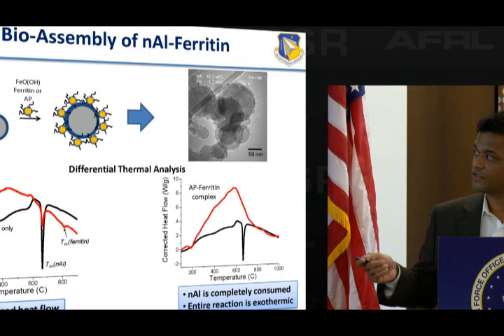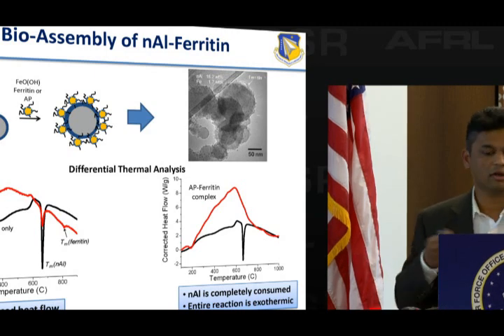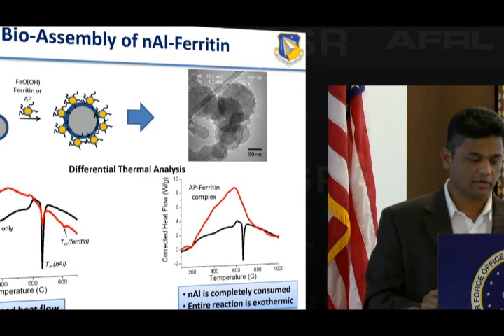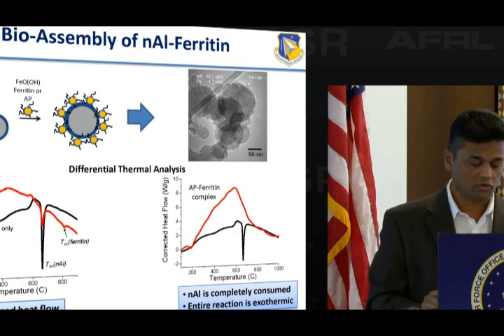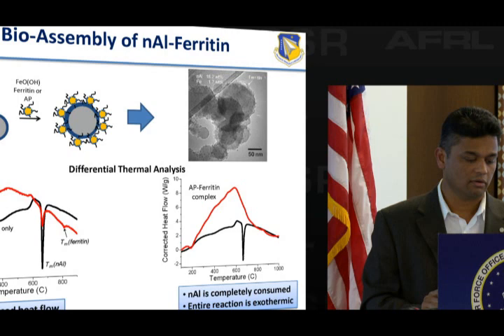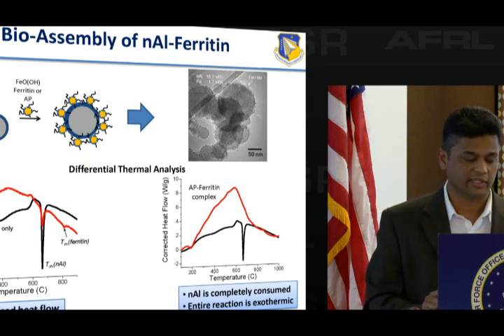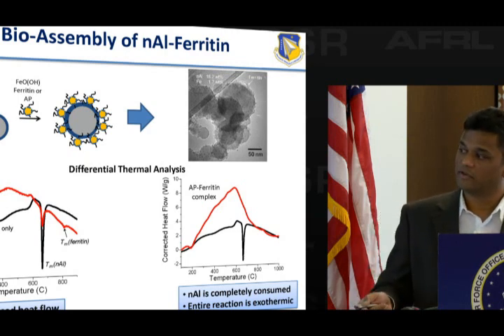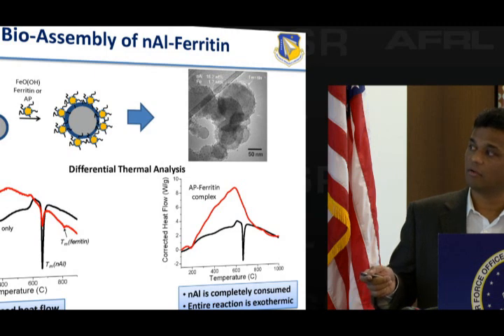So there's already iron oxide in there. Or you can bring ammonium perchlorate and load it in or put it on the outside. We tried all different kinds of tricks and asked, well, how does it behave? The first experiment: throw in ferritin, which has the iron oxide core, do differential thermal analysis, and compare it to nanoaluminum. The first thing we saw is an increased heat flow with the biothermite complex, which is ferritin with the nanoaluminum mixed together.